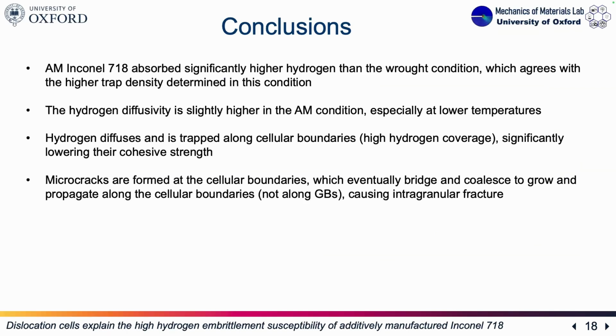So basically, what we can see is that in AM Inconel, the absorbed hydrogen was significantly higher than in the wrought condition, which agrees with the higher trap density determined in this condition. Then the hydrogen diffusivity is slightly higher also in the AM condition, especially at lower temperatures. Hydrogen diffuses and is trapped along cellular boundaries that have high hydrogen coverage, significantly lowering their cohesive strength. And then microcracks are formed at these cellular boundaries, which eventually bridge and coalesce to grow and propagate along the cellular boundaries, not along the grain boundaries in the case of the AM condition, causing this intragranular fracture.